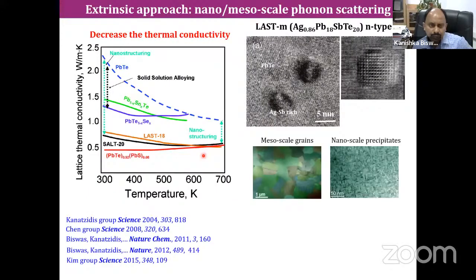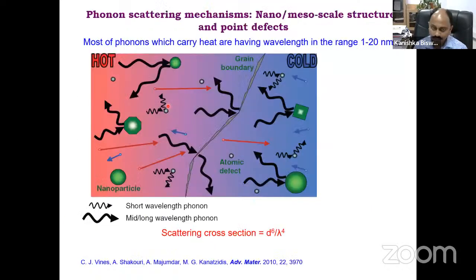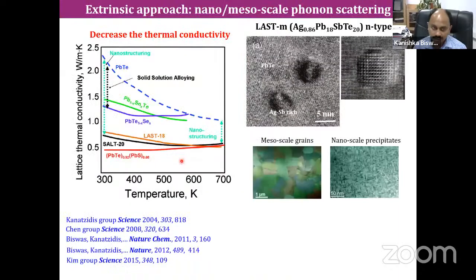So, for example, you see this lattice thermal conductivity versus temperature plot for lead telluride, which is a champion material. This is the high temperature plot for lead telluride, which is a champion material in this field. As I told you, when you create this kind of solid solution or point defects, the thermal conductivity decreases, but it does not go to the amorphous limit or glass limit. So that gave us a ZT of around 1 in this kind of material, which is known from the 1960s or 70s, mostly by Russians and scientists from the USA.